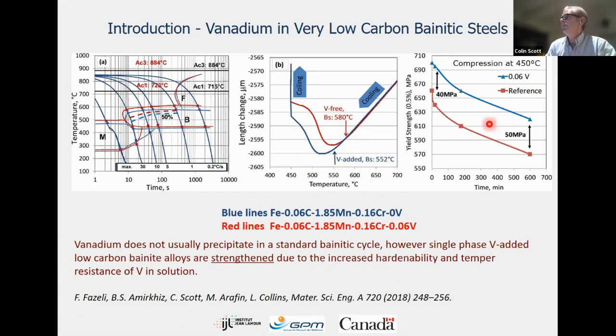And then there is this tempering effect as well. These are in situ hot compression tests done. So this is the bainite aging time, if you like. This was at 450 degrees C transformation for a 0.06 vanadium steel, 0.06 carbon as well. And you can see that we've got some gain from having vanadium in solid solution in terms of the softening kinetics of the bainite.